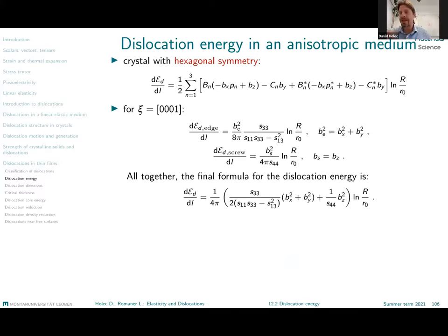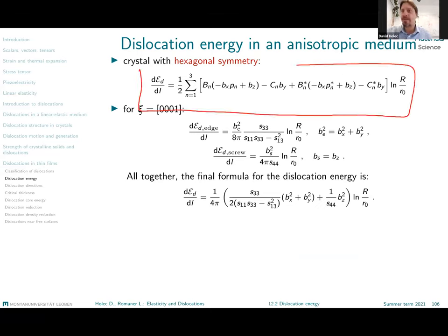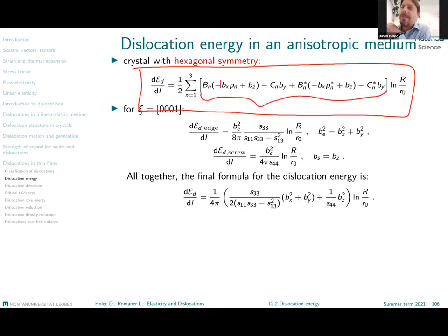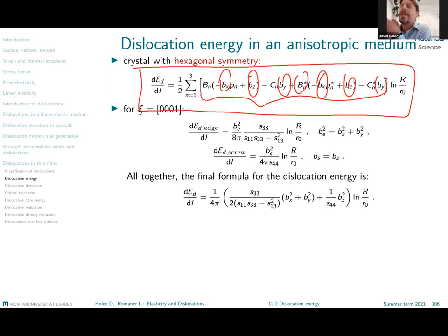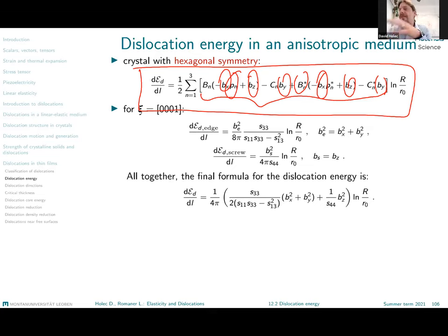What happens if we are not in an elastically isotropic medium? Well, things are principally the same — that's the easy part to say — but formally they become much more involved mathematically. You can see here a general formula for hexagonal symmetry, where you can again identify the pre-logarithmic term. We have the dependence on the components of the Burgers vector, and the coefficients bₙ, cₙ, and pₙ are some functions of the elastic constants of the hexagonal material. After this pre-logarithmic term, we have again the logarithmic dependence.